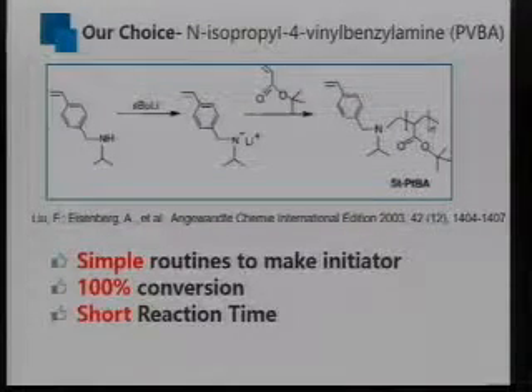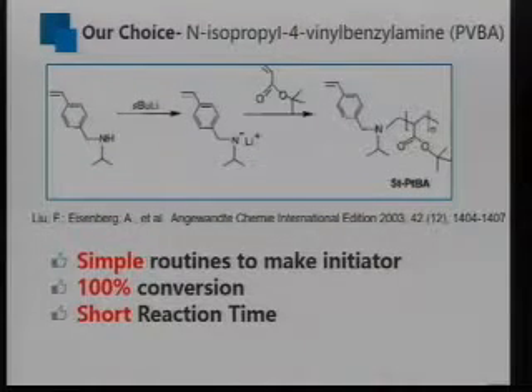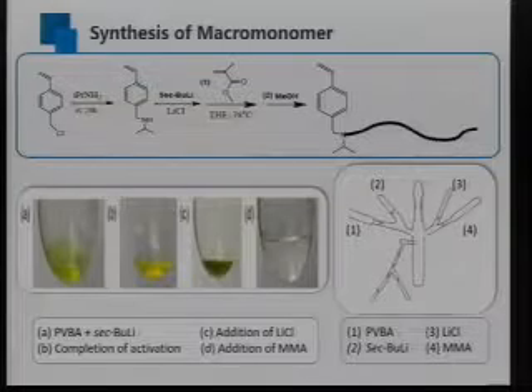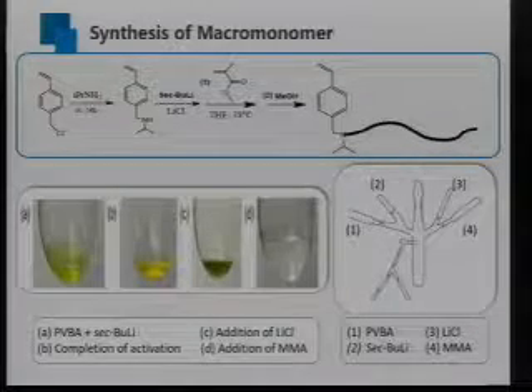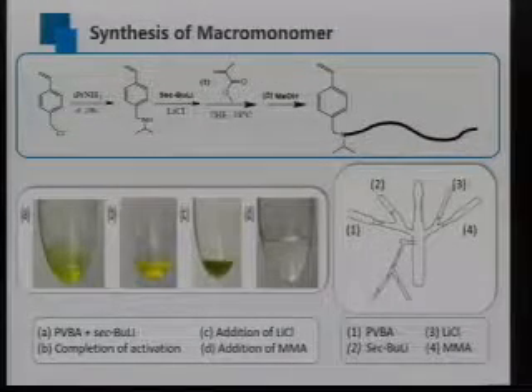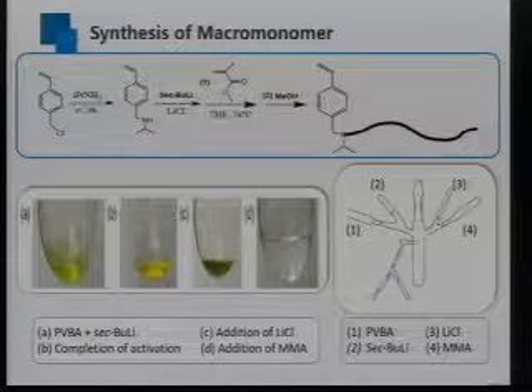After it is activated by the sec-butyl lithium, the formed nitrogen anion is too weak to attack this styrenic vinyl group, but strong enough to initiate the methacrylates. In this way, the macromonomer can be synthesized by anionic polymerization with 100% conversion and a reaction time as short as 1 hour. The initiator PVBA can be simply synthesized from 4-vinylbenzyl chloride with isopropylamine.